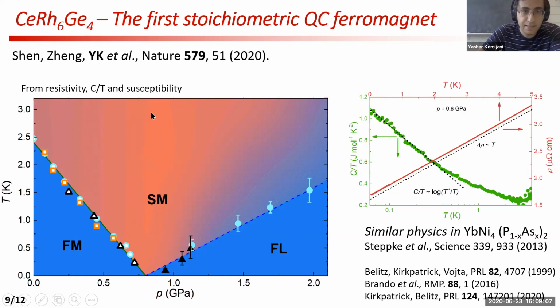So most of the quantum critical systems that we know, at least in heavy fermions, are anti-ferromagnetic, and there are few ferromagnetic systems, but they are usually disordered, or the tuning parameter is a disorder. And it turns out that this is the first stoichiometric quantum critical ferromagnet. And moreover, right at the critical point, the resistivity shows this linear temperature dependence, and the specific heat shows this logarithmic temperature dependence.